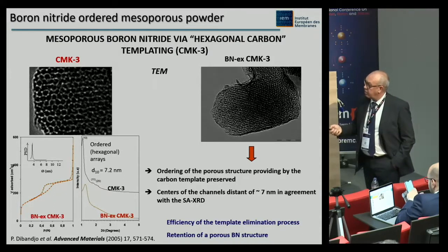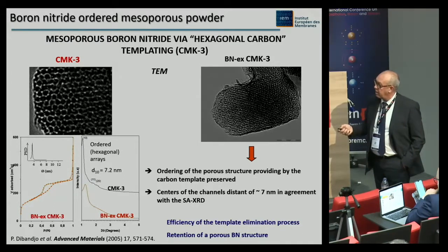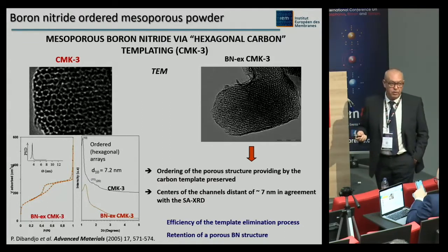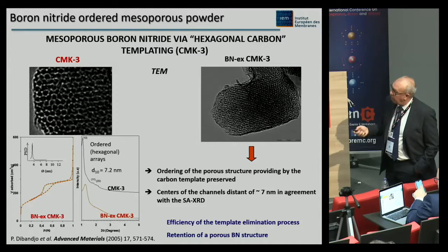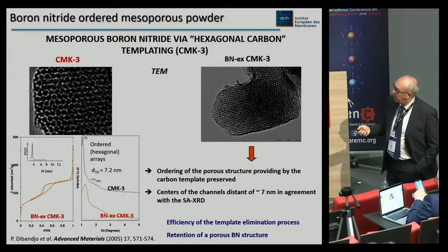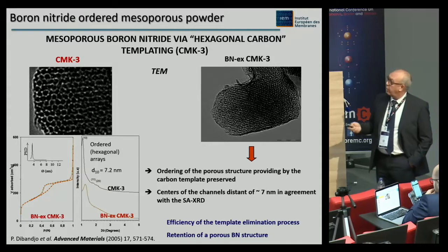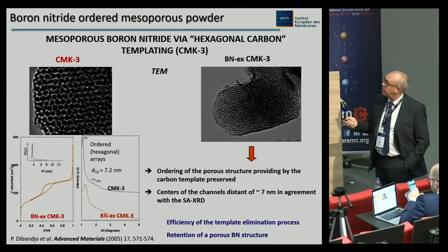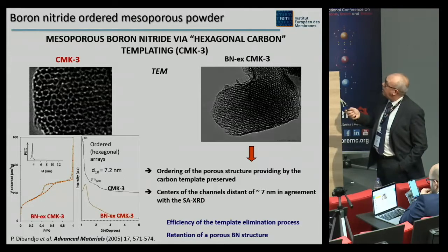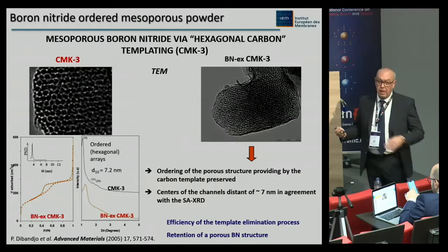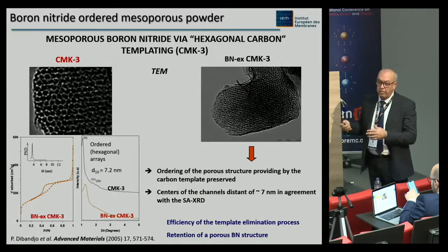At the beginning here, the nitrogen adsorption analysis, which shows the mesoporous character of the ceramic, of the BN, and here's the small angle X-ray diffraction data showing the organization of the porosity. Here it's for the carbon, here it's for the BN in the powder, and this has been confirmed by the TEM images. Here's the carbon, you can see the hexagonal organization of the porosity. And here is the boron nitride with some organization also of the porosity. And this structure is a replica of this structure.